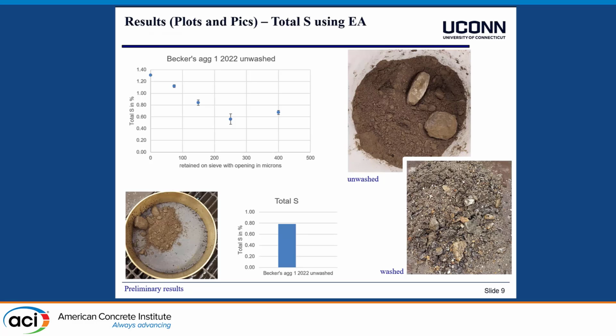When we crush this, we can also sieve it in different sizes, but we at least attempt a number 40 sieve and smaller. If it's above 40 sieve, then we crush it finer. And if you take those fractions and the weights, then you also come up with an average total sulfur amount. For example, in this case, it's 0.8% or around.